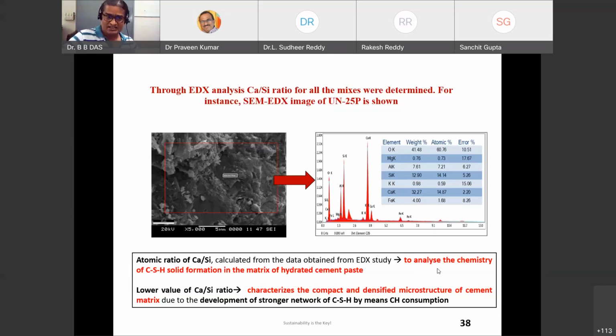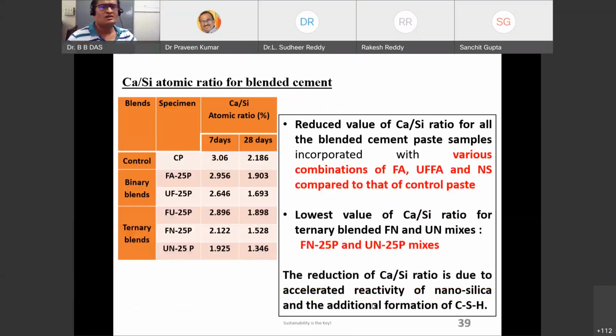It will analyze the chemistry of CSH formation in the matrix of hydrated cement paste. How can you characterize it? For example, a lower value of the Ca/Si ratio characterizes a compact and densified microstructure of the cement matrix, due to the development of a stronger network of CSH. Remember, if the calcium is showing less, it means most of the calcium is consumed with the silica particles, and the calcium hydroxide has reacted with the silica to form calcium silicate hydrate.